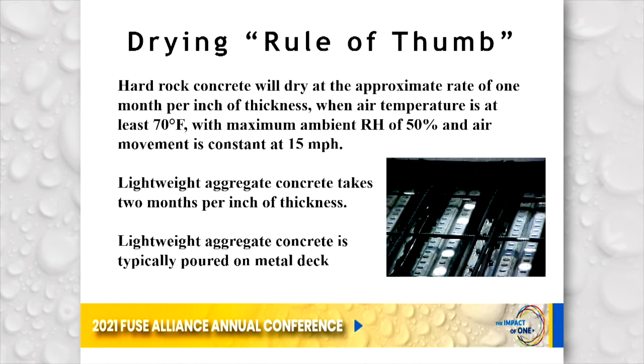Now, lightweight aggregate takes about 2 months per inch of thickness, and we've already touched on why, and that is that the lightweight aggregate contains a lot of water that has to slowly dry out of the concrete. And that lightweight aggregate concrete, and I think I said it earlier, is typically poured on a metal deck.